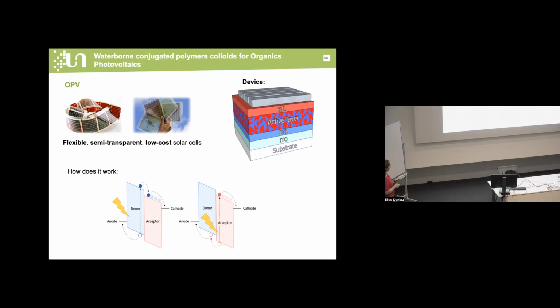in order that upon absorption of an incident photon, the electron undergoes an electron transfer from the donor to the acceptor, from the LUMO of the donor to the LUMO of the acceptor, whereas at the donor-acceptor interface, a hole is created, which is transferred to the donor. And then both materials will transport the charge inside the active layer through their respective materials, and then arrive at the respective electrode.